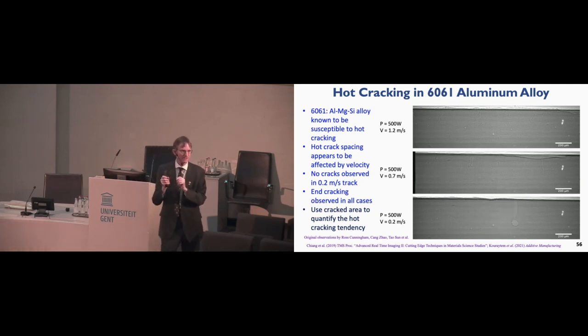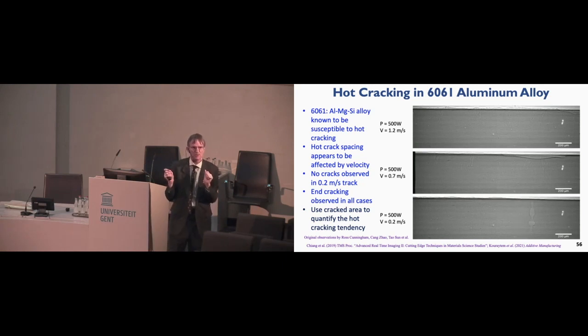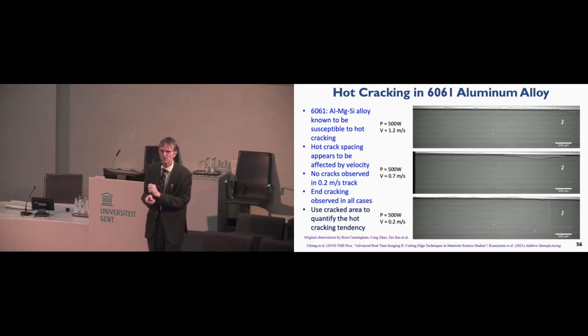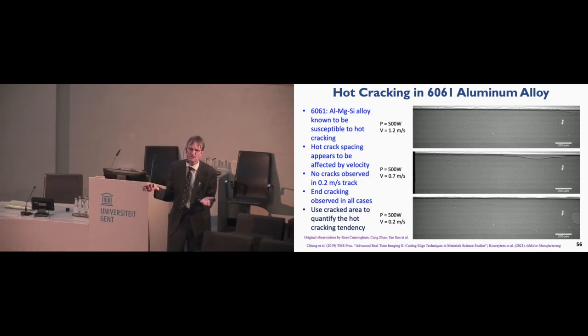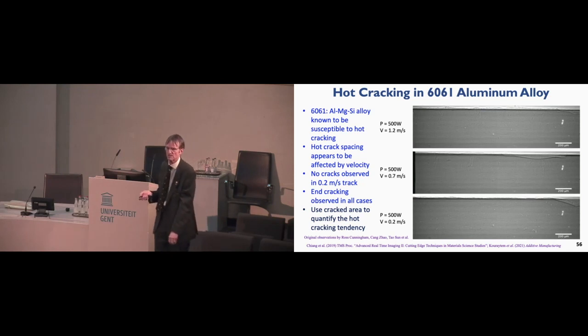And this is 6061. 6061, as it comes, is notoriously prone to hot cracking. And so you cannot just buy 6061 powder and go print with it, because your part will be riddled with cracks. It will be quite useless. Now, I'm well aware that you can modify aluminum powders and do things about it, but this is the basic result. So we decided that we would try to quantify this, use the cracked areas to quantify the tendency to hot crack.